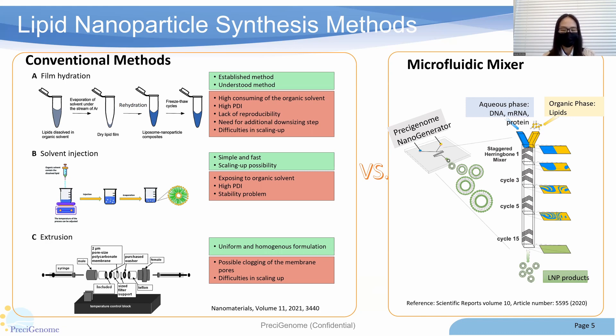On the other hand, microfluidic mixing is a reliable and convenient way to prepare lipid nanoparticles. The schematic here shows the mechanism of the microfluidic mixing method. Two streams — one is aqueous phase including the DNA, mRNA, or protein — will mix with another stream, usually lipids, in a thin mixing channel. By controlling the total flow rate of the two phases, users can synthesize lipid nanoparticles in a consistent way. Usually higher flow rates will generate smaller particles. The homogeneity of the microfluidic method is very good; the PDI generated by this method is usually below 0.2.